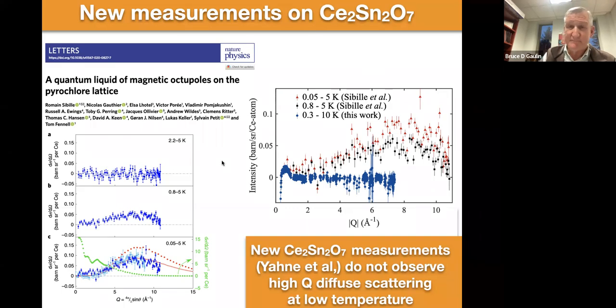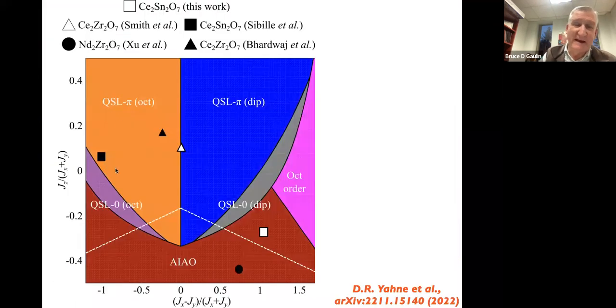So at any rate, in the case of cerium zirconate, we have our work as the open triangles. There's also other work that Pengcheng was involved in, and again, it's work that I can find no fault with. There's a pretty consistent picture coming from these independent studies of cerium zirconate, all consistent with a quantum disordered liquid state that might be akin to quantum spin ice. For cerium stannate, there seems to be quite a significant discrepancy between where this new study places it and where the original study placed it.